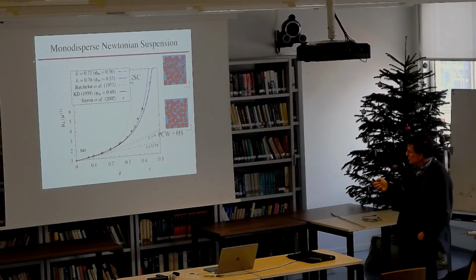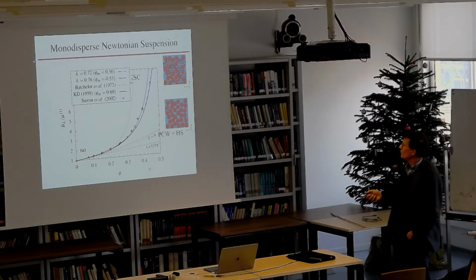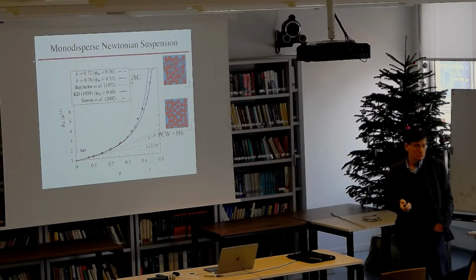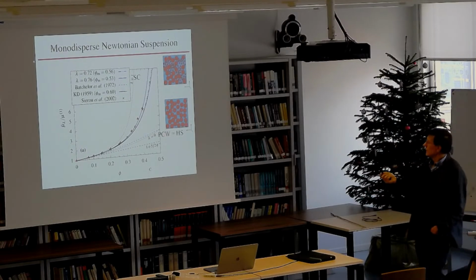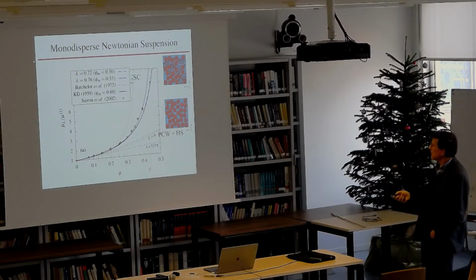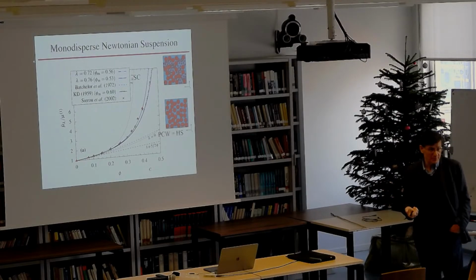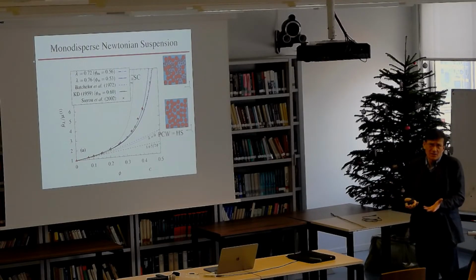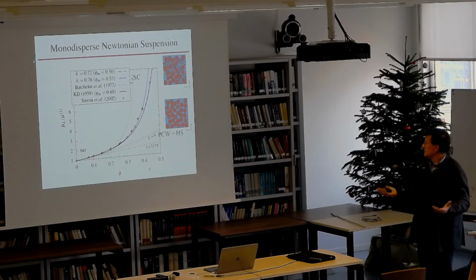Now why did we choose this value, 0.72? We can try to fit the data, and we can do that pretty well with 0.76, right? That's the blue line, and it agrees very well with the experimental data. But then, if you have to do that for every microstructure, it gets a little bit complicated.